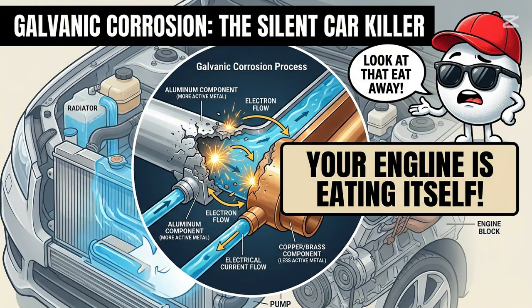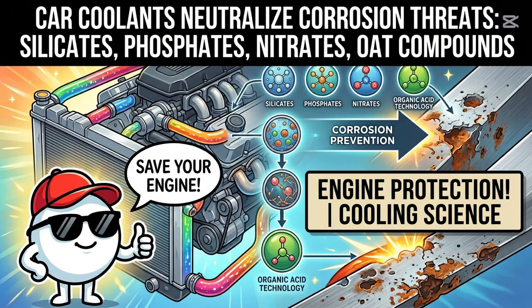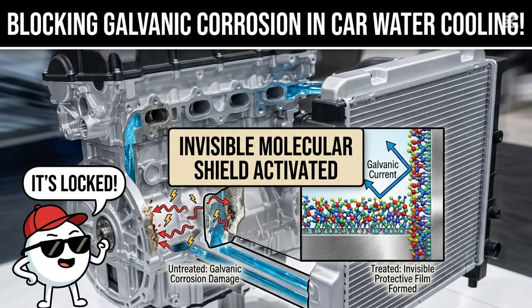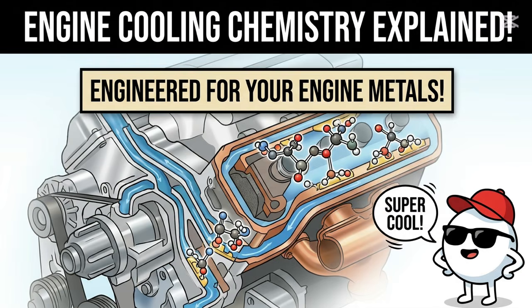One metal is more electrochemically active than the other, and it starts sacrificing electrons, literally giving up material, to the less active metal nearby. This is galvanic corrosion, and it's a real, measurable electrical current flowing through your cooling system every time the engine runs. This is precisely the threat that commercial engine coolants are engineered to neutralize. Modern formulas contain sophisticated corrosion inhibitors, silicates, phosphates, nitrates, and in newer formulations, organic acid technology compounds, that chemically bond to the metal surfaces on a near molecular level, forming an invisible protective film that blocks the galvanic current from doing damage. It's genuinely advanced chemistry, engineered specifically for the combination of metals sitting in your particular engine.